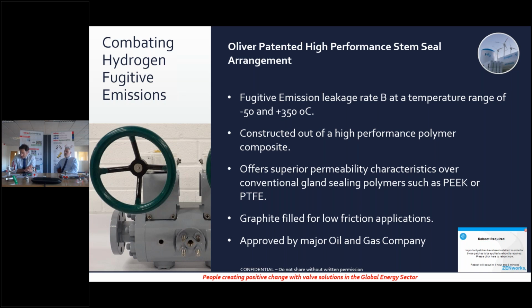We also patented the idea, and then later found that actually this was tested with helium, and as mentioned earlier, there are very similar permeability rates to hydrogen, and it is perfectly suited to hydrogen applications. In fact, just to give you an idea, the permeability rate of the material we were using is about 100 times better than conventional PEEK seals. So not only could we do the temperature range, but this gave us a perfect solution for hydrogen applications. After all, really, the valves that we're talking about, the primary focus is for them to be isolation valves.